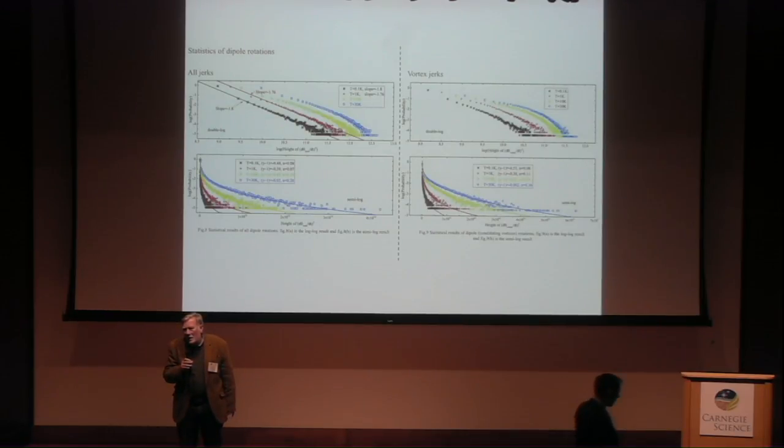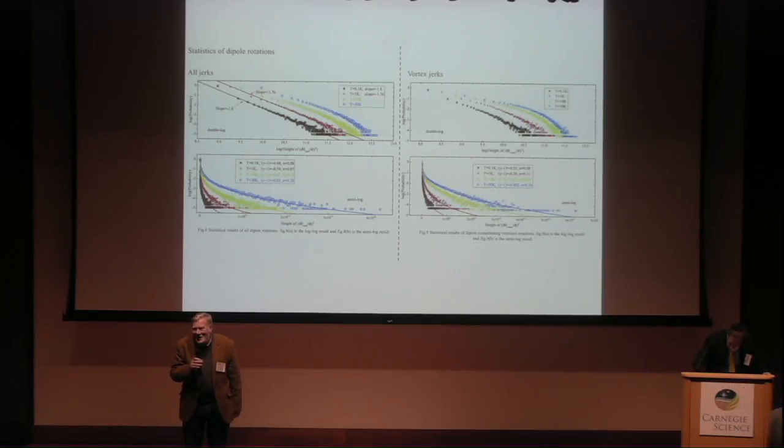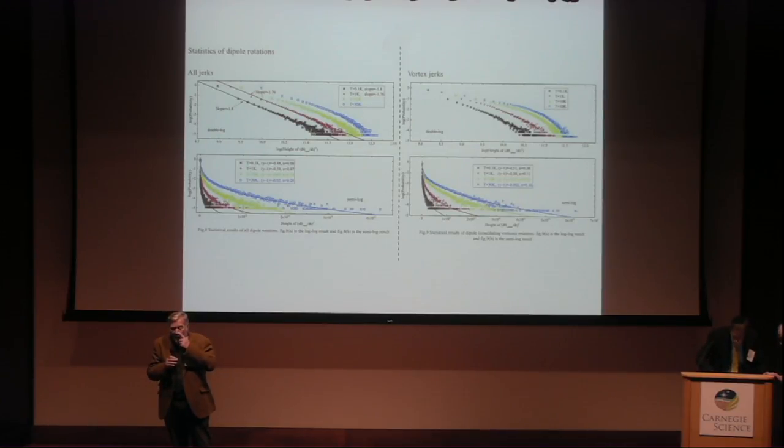But you cannot tune that by, for instance, changing the length scales of the domain walls? No, we can't do that. I mean, the thickness of the domain wall is fixed. Did you ever try to manipulate the walls? Yeah, that would be interesting. We can, I mean, so far the superconducting properties are completely independent of how we make the walls. We can dope them with sodium, lithium, potassium, or we can just take oxygen out. And the currents and JC and all this stuff is exactly the same for all of them.